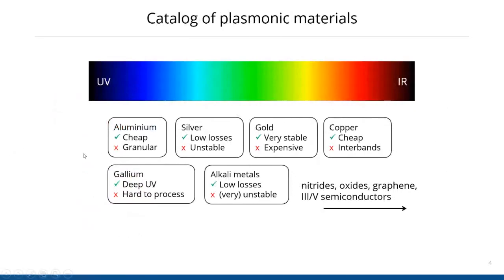There are various types of plasmonic materials with good plasmonic properties, each with their own advantages and disadvantages, operating in different wavelength regimes. Aluminum, for example, is good for ultraviolet plasmonics, whereas gold is used a lot for visible and near-infrared plasmonics, also because of its stability and convenience in nanofabrication. Going further into the infrared, there are also compound materials that show plasmonic properties. But today we'll mostly consider metals.